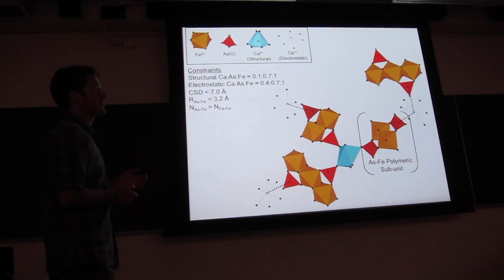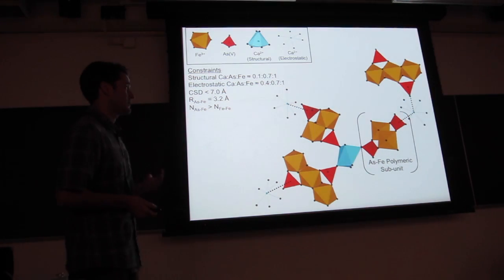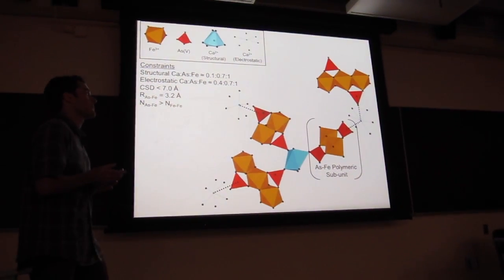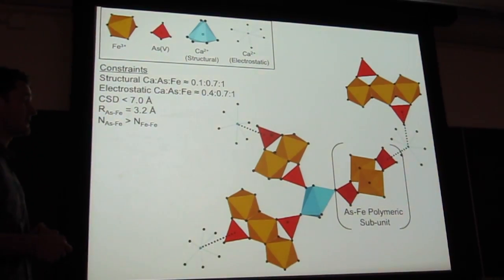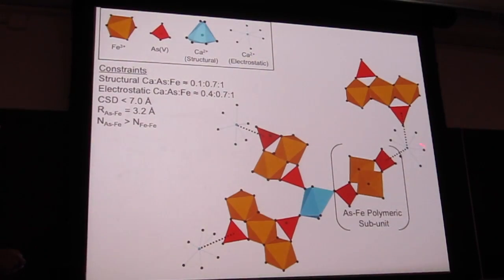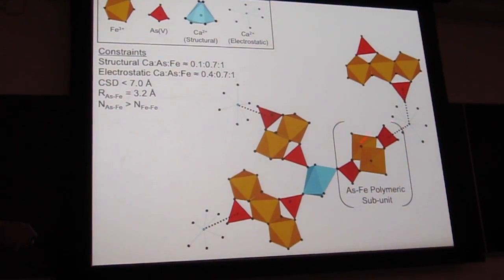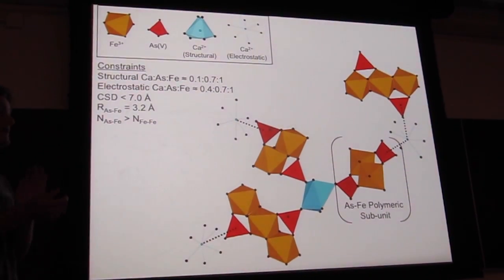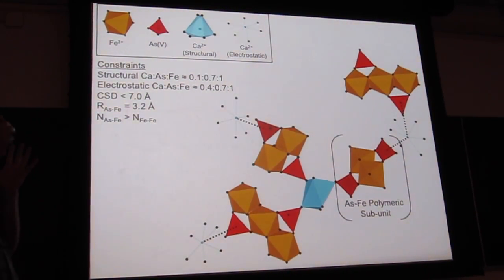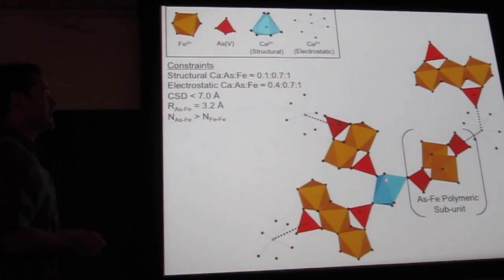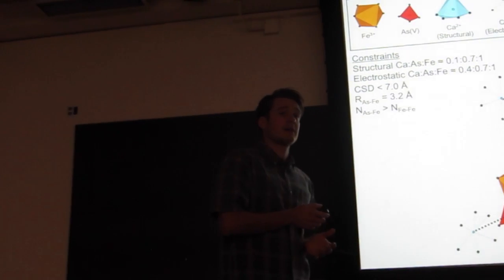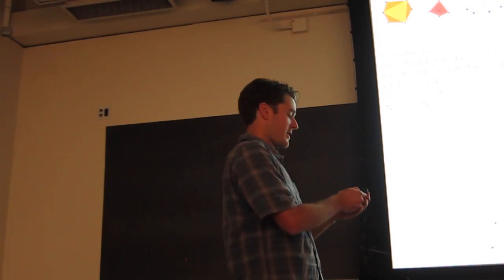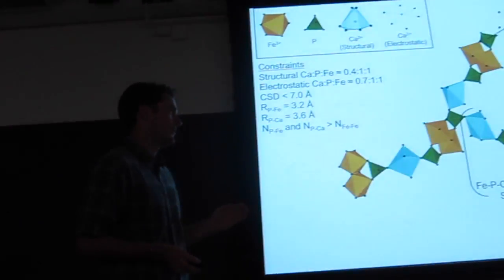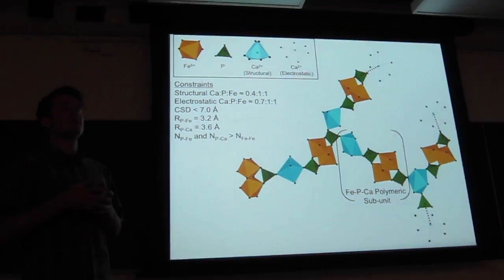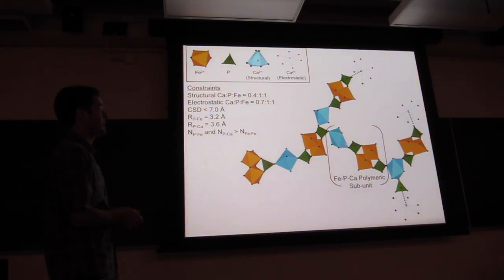And in this model, calcium enhances arsenic uptake in two ways. So one, electrostatic calcium neutralizes surface charge. So arsenic is negatively charged at neutral pH, and calcium is positively charged, and so calcium associating with these polymeric subunits neutralizes the surface charge and minimizes long-range repulsive forces from arsenic coming onto the iron oxide and binding. And structural calcium enhances arsenic uptake by forming chemical bonds. Okay, so the phosphate 500, or the P500 plus calcium sample is here, and really the only difference between the two is that in this sample you have a much larger fraction of strongly sorbed or structural calcium. And so that's what we see here.